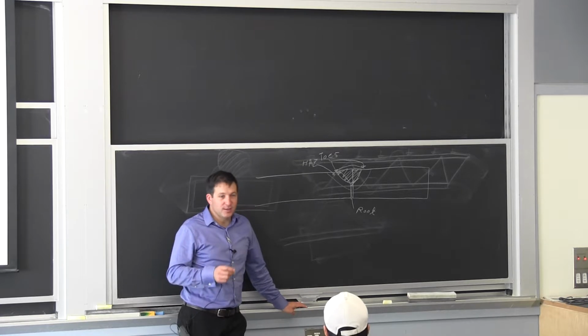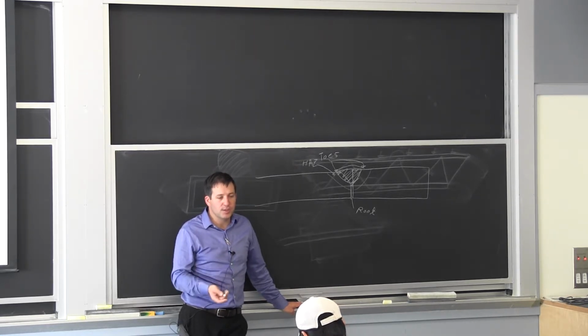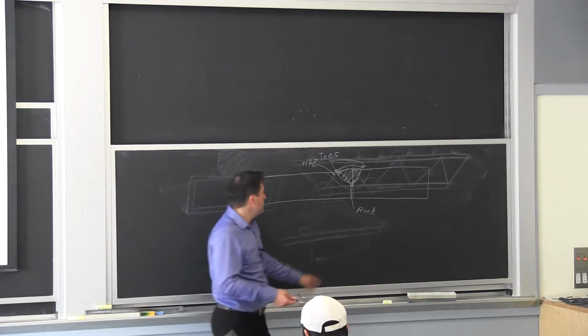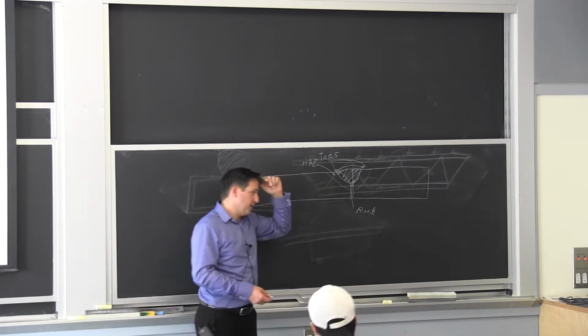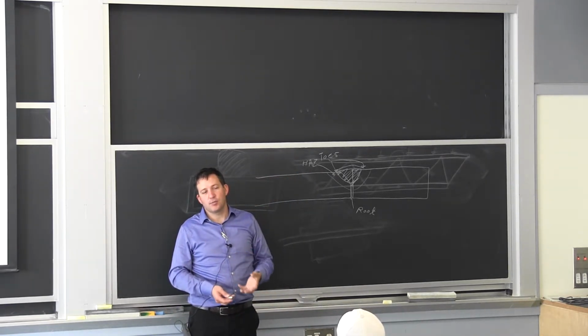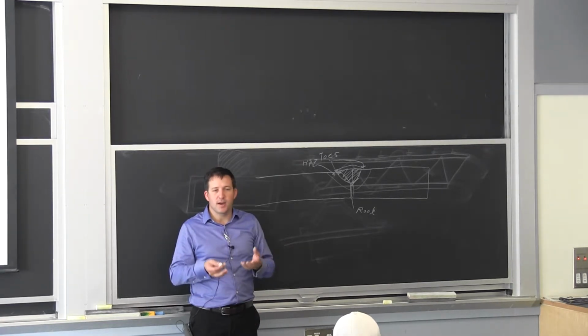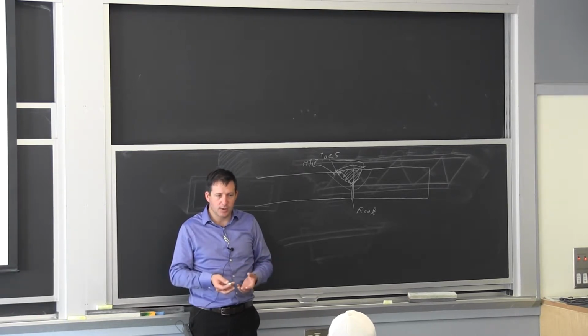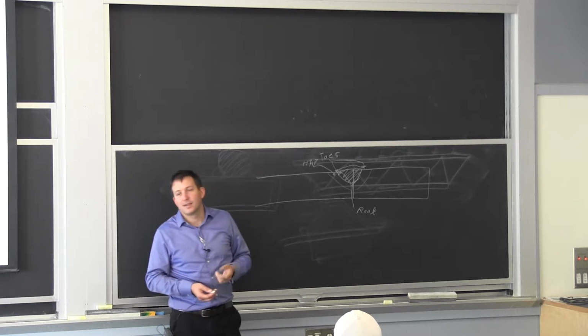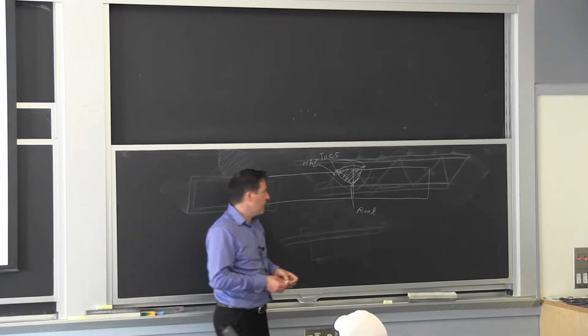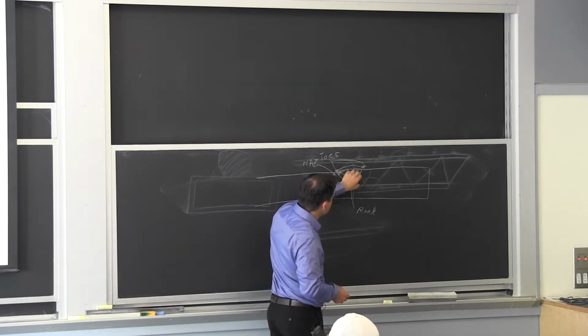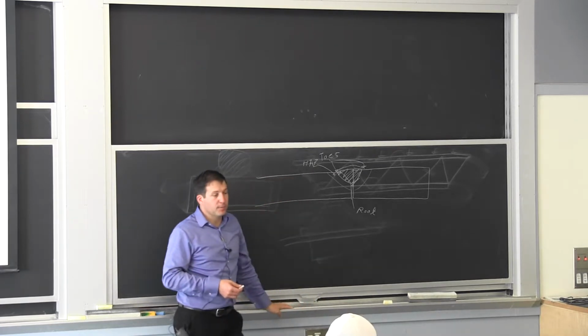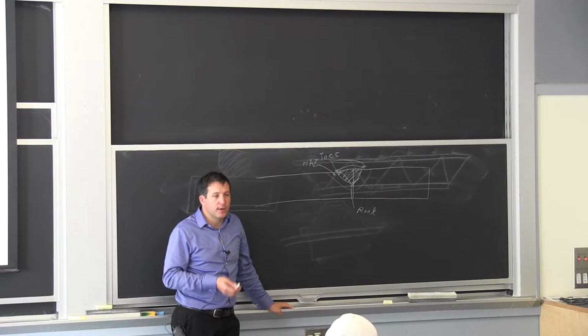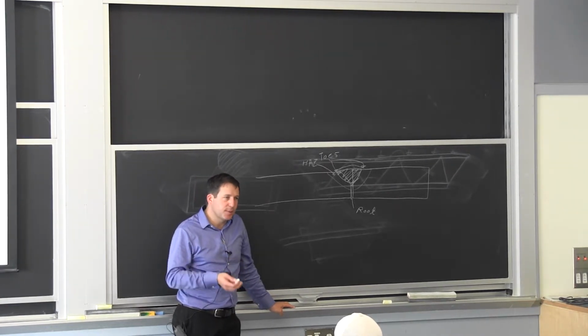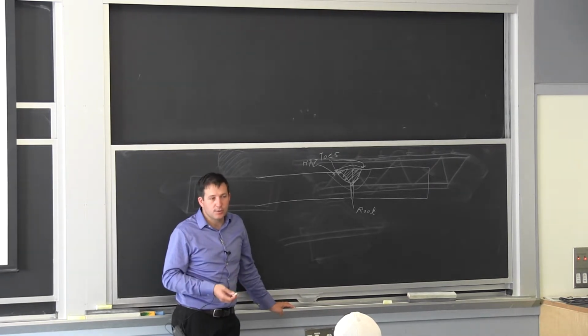With aluminum, it's slightly different, because if you remember, when you quench aluminum, you just freeze the microstructure, and then you go and age it. So what you lose in the heat-affected zone with aluminum typically is that strengthening effect. You're going to remelt these fine precipitates that are giving you strength, and when it's all done, you have a low strength aluminum. If I test the properties of the heat affected zone in steel, most of the time it's going to be a much higher strength, lower ductility. The typical aluminum alloys do have that aging process, and because you lose the aging, you become much softer in that heat affected zone.